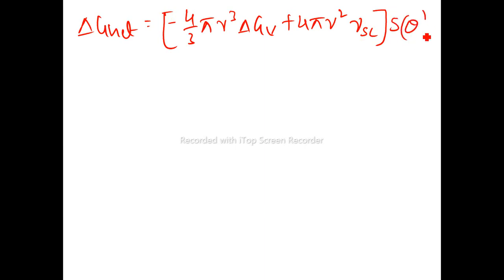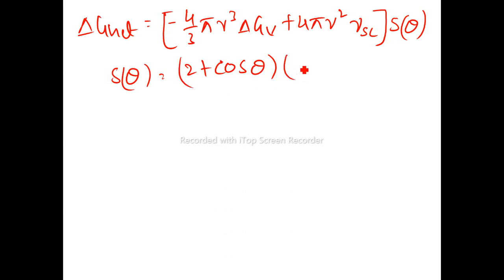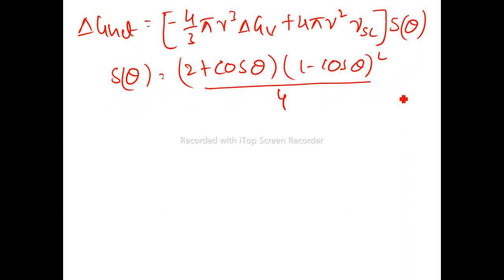...a new term called the shape factor S(theta). We will get that S(theta) can be written as: (2 plus cos theta) times (1 minus cos theta) squared, whole divided by 4. Deriving this shape factor equation is outside our syllabus right now. If you need it, I will make a separate short video of about 10 minutes to derive this expression.